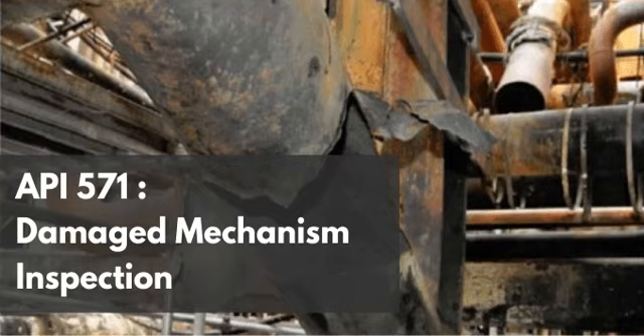Yeah. And once the film ruptures at that tiny crevice, the localized chemistry within the crack tip becomes even more aggressive than the bulk fluid. It drives the anodic dissolution deeper and deeper into the web of grain boundaries. Which naturally brings us to the material itself. The documentation establishes that carbon steel and low alloy steels are the primary susceptible materials here.